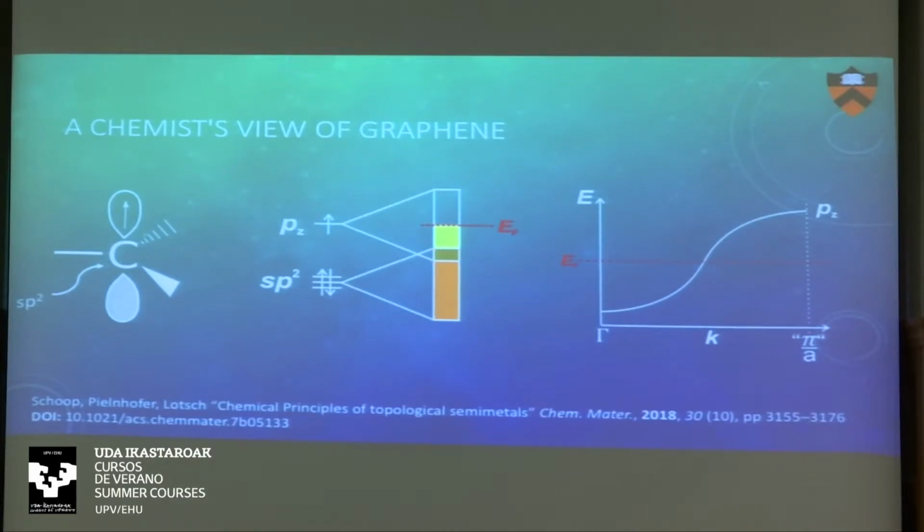So if we draw roughly the Roald Hoffmann band structure, we have 1 half-filled band. It would look like what we draw for a single chain of hydrogen. I know this is hexagonal and there's a little bit of different symmetry, but let's ignore this for now. So we have a half-filled band. This intuitive chemist picture describes why graphene is metallic in the sheet, but it doesn't explain why it's a topological semimetal or why it has a Dirac cone.